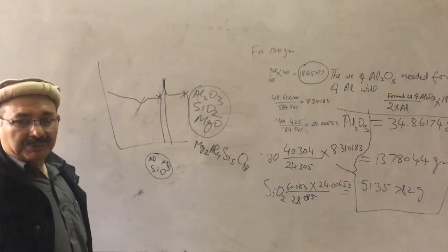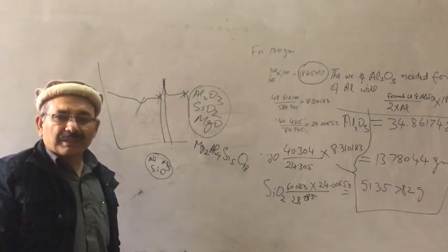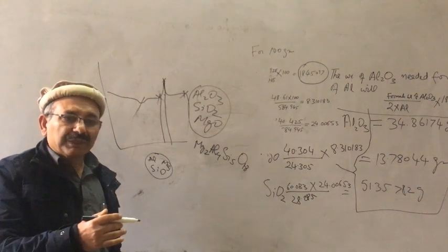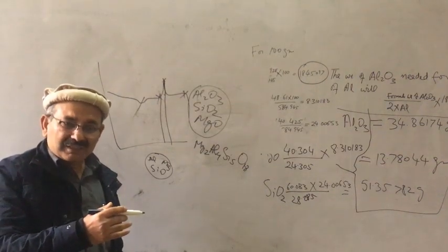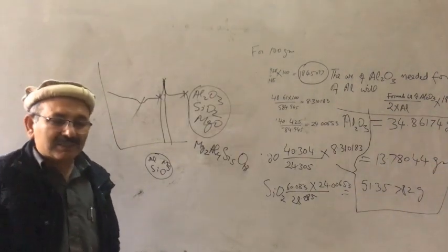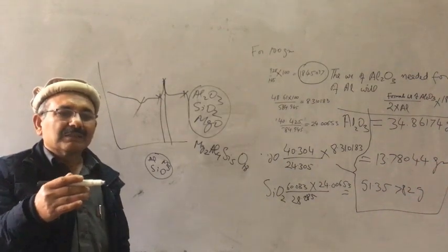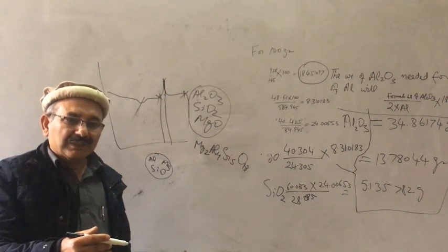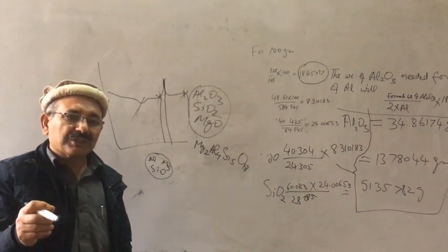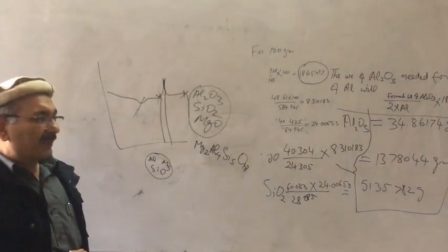But it depends upon you what sort of experiment you are doing. There are glass ceramics where you control the crystal size. In these materials, the lower the temperature, the smaller the crystal size. The higher the temperature, the larger the crystal size. Smaller crystal size favors highly dense materials. Larger crystal size favors less dense materials, because many voids and gaps occur when the crystals are large. They don't fit into the gaps, and pores and voids are left there.